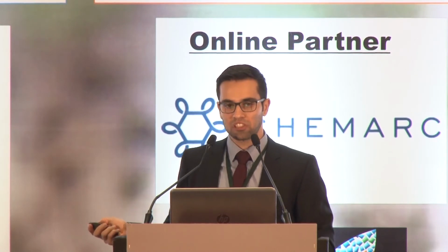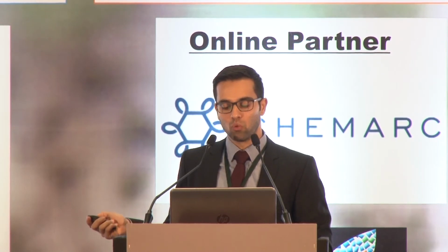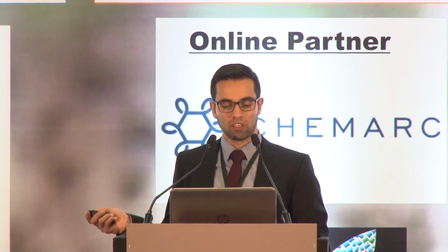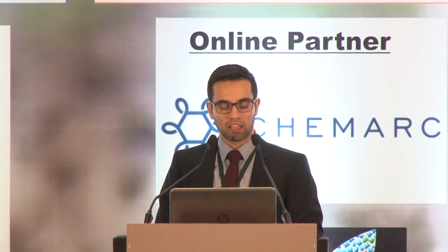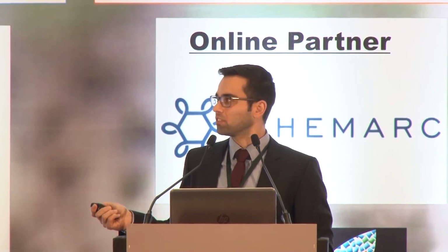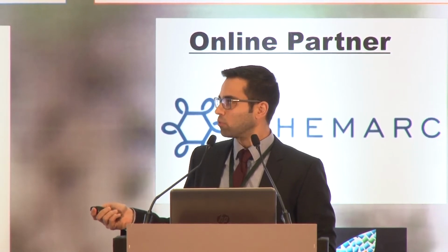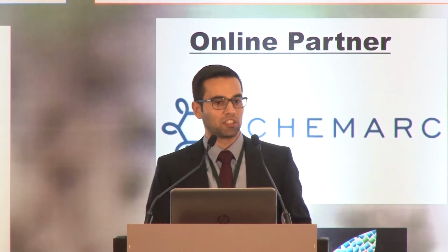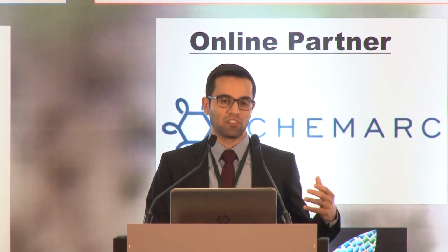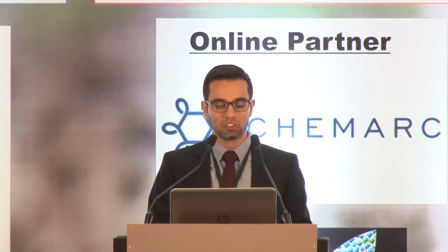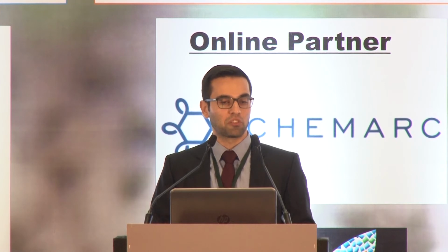So after 80 weight percentage, you will get 1.2, 1.9, 2.4, 3 watt per meter Kelvin at 90 weight percentage. And the 4, that's not commercialized yet. That's still in development. But we promise that we can reach, in certain polymers, depending on the thermal conductivity of the polymer and the filling degree, up to 3 watt per meter Kelvin through plane.